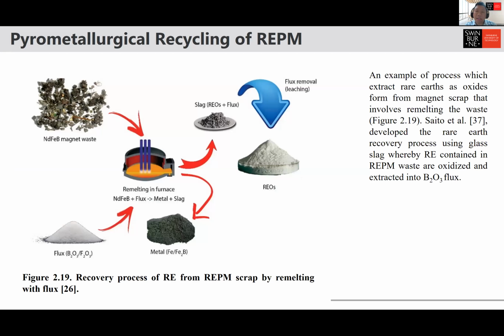This is the thing that I mentioned earlier. So in here, we use boron oxide, basically, to make some slag, right? From the NdFeB. So in here, we have NdFeB magnet waste. You already make it into small pieces in there. You crush it, right? And then you put it in a remelting furnace. This can be an electric arc furnace or other types of furnace, yeah? And then you mix it with boron oxide as a flux, right?